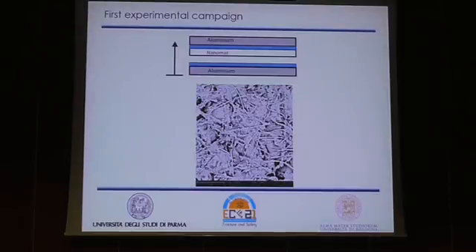This is the stacking configuration of the nanomodified specimen after the breakage occurred. SEM analysis revealed that both the virgin and the nanomodified specimens present a relevant level of porosity, probably due to a high viscosity of the resin, which prevents the complete ejection of the air. In the nanomodified specimen in particular, the level of porosity was very high because the nanomat does not succeed in evacuating completely the air trapped within, which results in a decrease of the mechanical bonding properties. Furthermore, the resin does not manage to fully impregnate the nanomat, which contributes to making the bonding process fail.